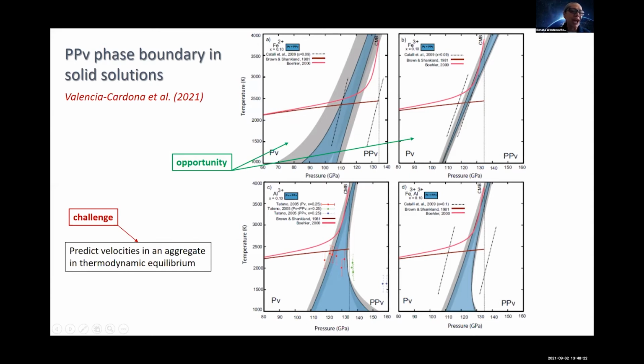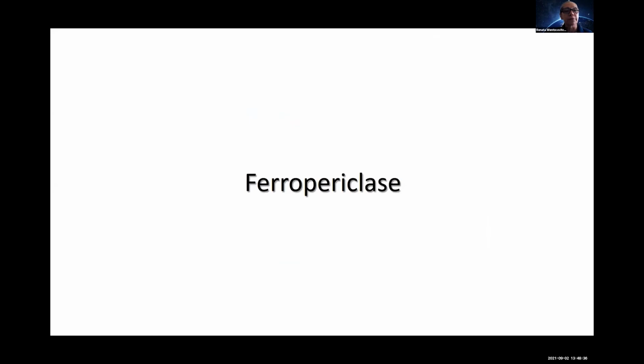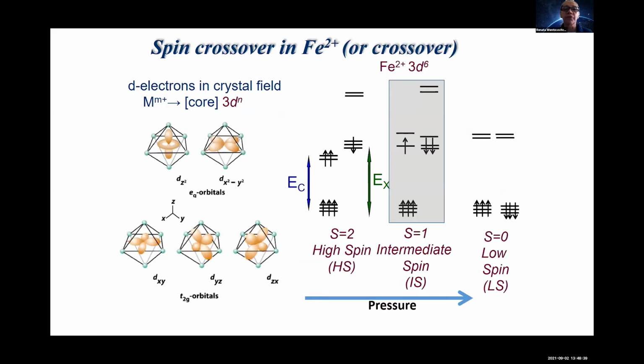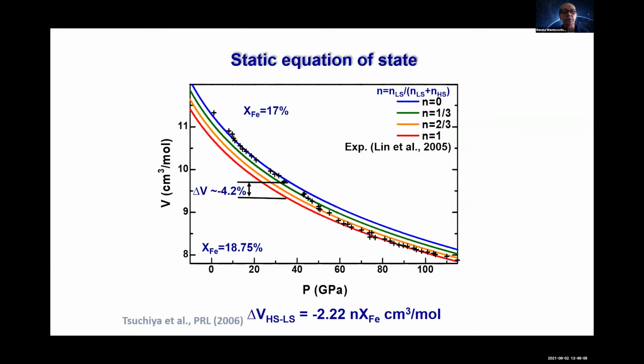So this is an opportunity, but the challenge in investigating velocities is to really reproduce velocities in thermodynamic equilibrium in an aggregate. This is the real challenge because these are strongly correlated systems. So ferropericlase is celebrated for its spin transition. Ferrous iron has 6 d electrons: 5 electrons spin up, 1 electron spin down in the d orbitals, and you have a high spin state at low pressure. The crystal field splitting increases the energy distance between the triplet and the doublet, and we end up with 3 electrons spin up and 3 electrons spin down at high pressure. This is the spin transition, and it also occurs in ferric iron.